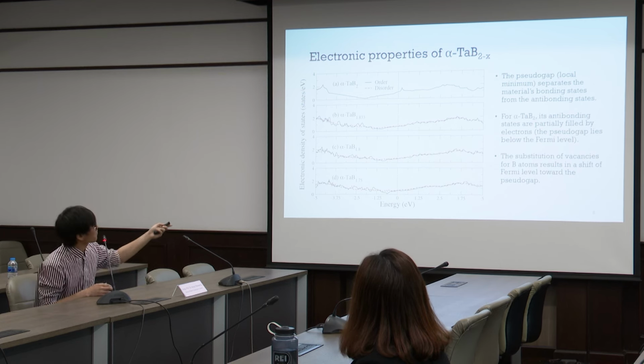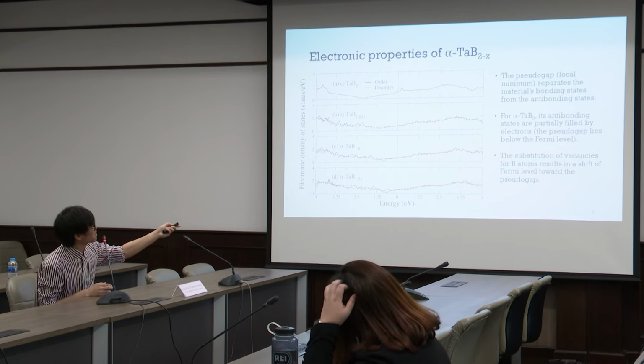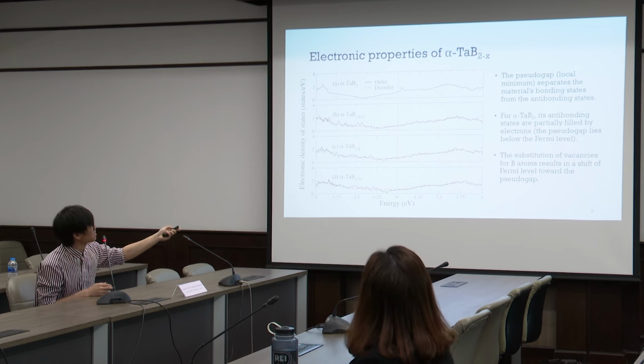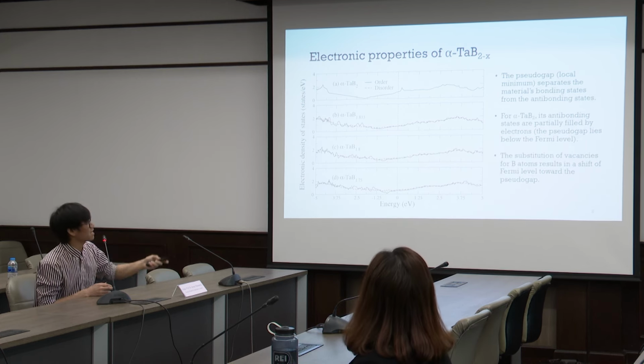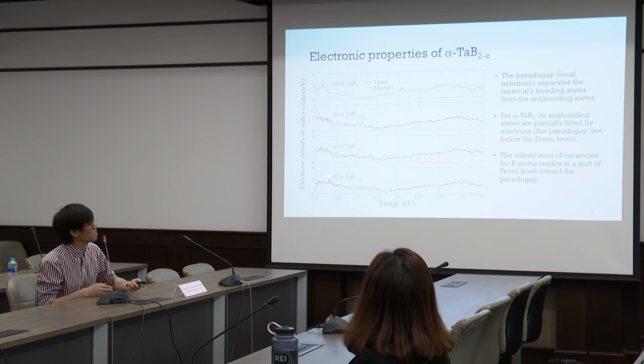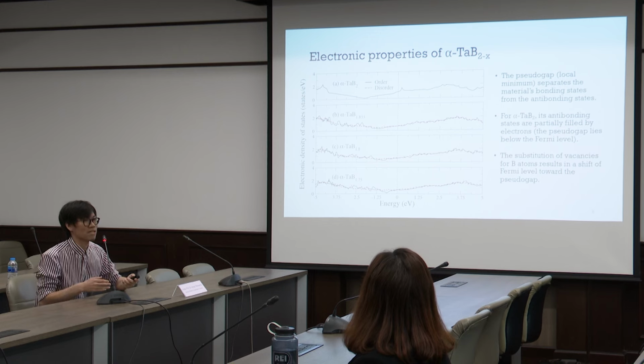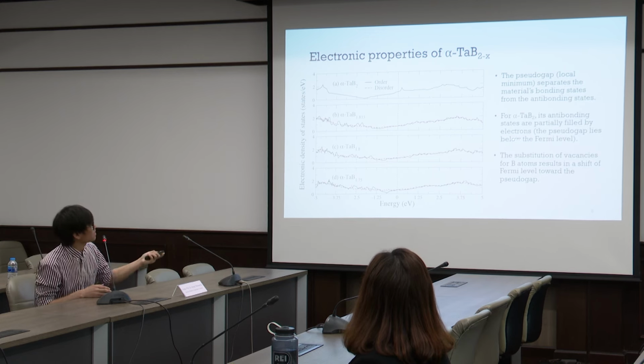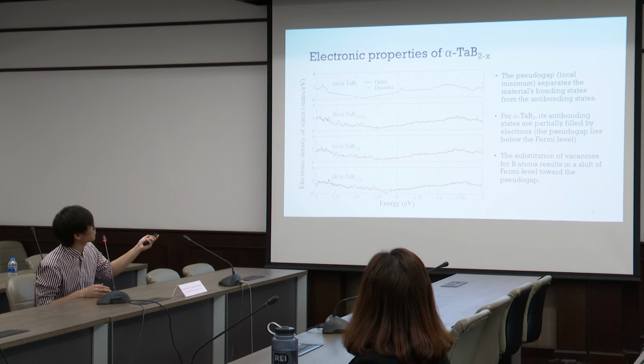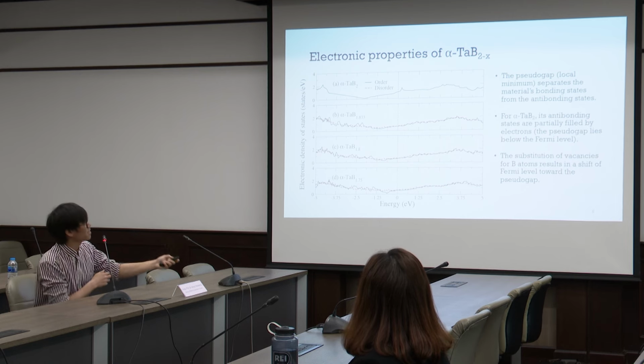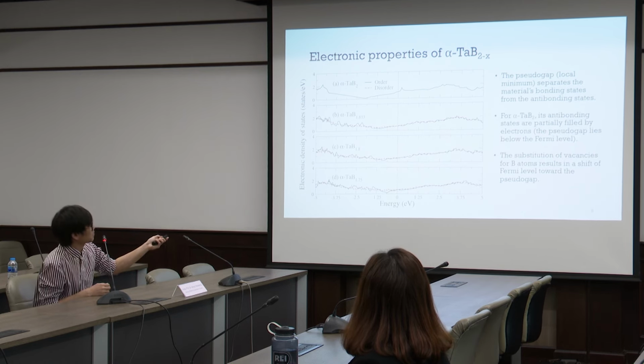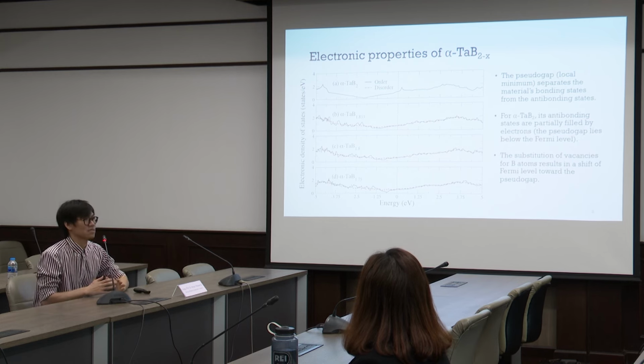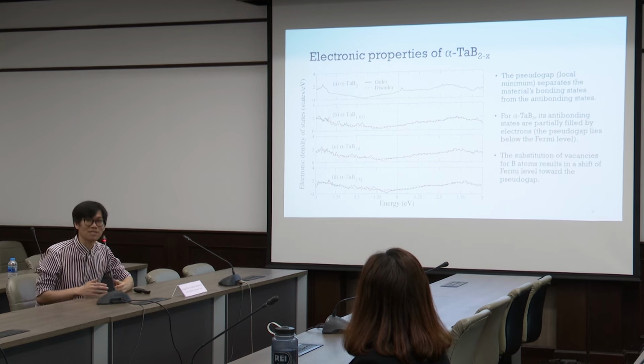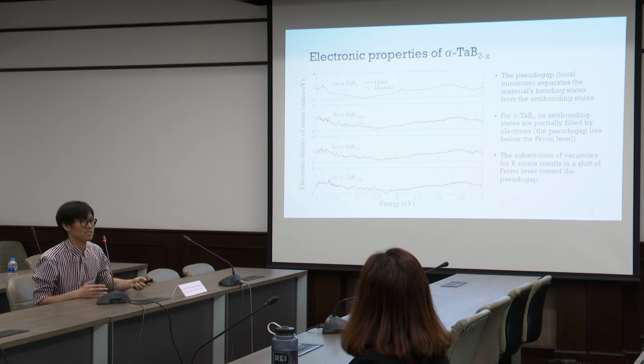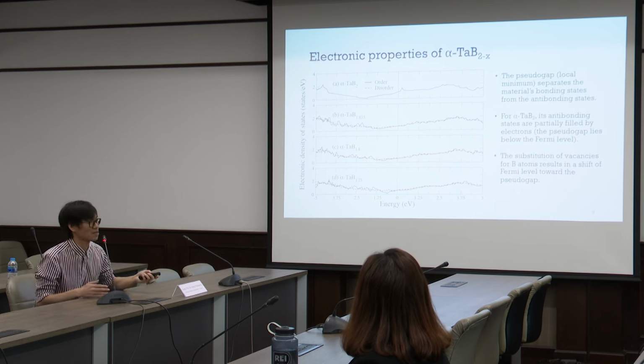For the stoichiometric TaB2, you can see that the Fermi level, which is this vertical dashed line, is to the right of the pseudo gap. This means that some anti-bonding states of this TaB2 are partially filled by electrons. But when there exists vacancy in this material system, with B2 reduced to B1.8 or B1.75, the Fermi level shifts toward the pseudo gap. This indicates a reduction in the number of electrons filling the anti-bonding states, and that increases the stability of the material and also the mechanical performance.